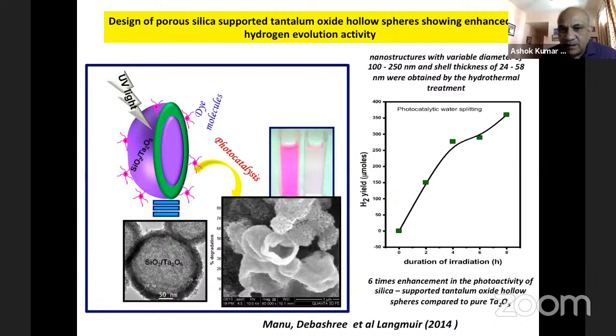I think this may be another design where we are now using two semiconductors for two different reasons. We are using porous silica, which is a very high band gap, not for absorption of photons, but as a support, as an adsorbent to adsorb the organic medium such that the efficiency of photocatalysis goes up. So we design this kind of cup-like structures. This method of synthesis is a little intricate, how you get these cup-like structures and how you get the rim on the surface. So you see this is a TEM where in the core the contrast shows, and then we did EDAX, the core is only made up of silica, whereas the rim has got a deposition of tantalum oxide. Now, why one does this is you want minimum use of an expensive material like tantalum.